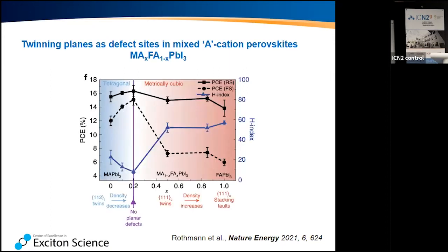And in a nutshell, what we could see is that there's a correlation between the twinning and the performance. At this magic combination at 0.2, we don't observe any twinning, and that's where the hysteresis index is the lowest, and also the efficiency of our forward and backward scans has a maximum. So we think that there is a correlation between those twinning planes, the defect being the twinning plane, and the performance of our solar cell. There's also a theory that the twinning planes allow for enhanced ionic conductivity. That's also why the hysteresis index is quite high where there are twinning domains and quite low where you do not have them, because you cut down these ion migrations.